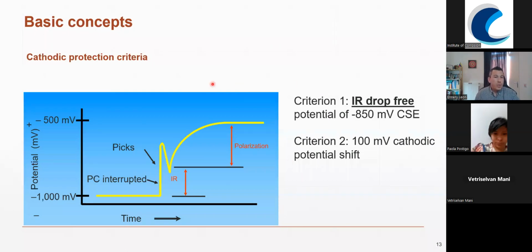And talking about the cathodic protection criteria, basically we have two of them. The first one is the IR drop-free potential of minus 850 millivolts versus copper sulfate electrode. Because a steel structure is considered to be protected when it has a structure-to-electrolyte potential, the electrolyte could be water, could be soil, of at least minus 850 millivolts or more negative, meaning that it could be minus 950, minus 1 volt, but it has to be at least minus 850.